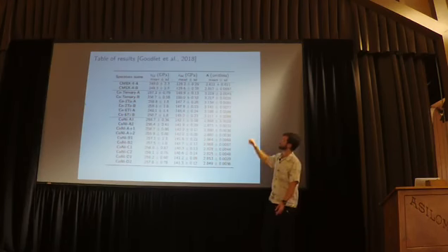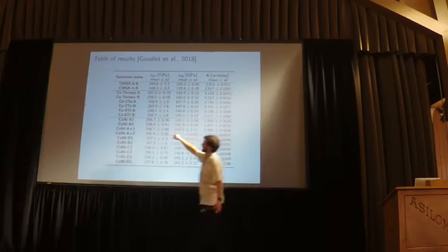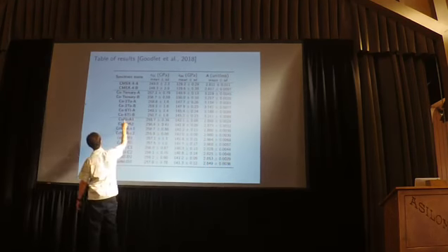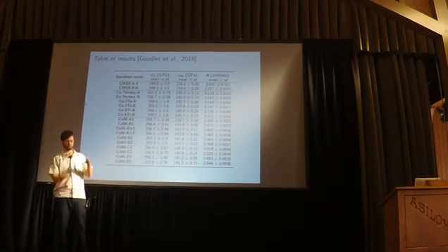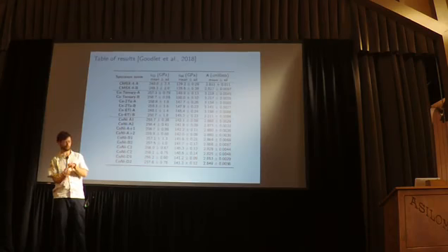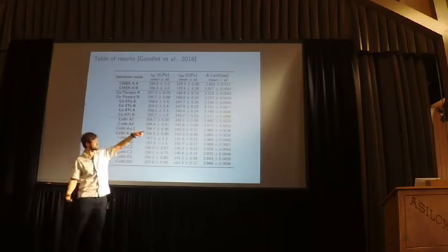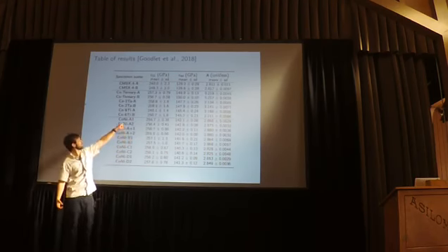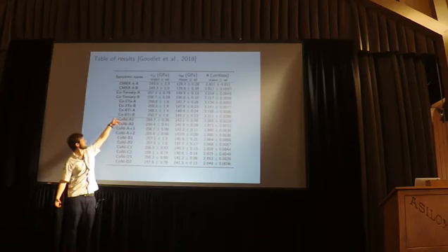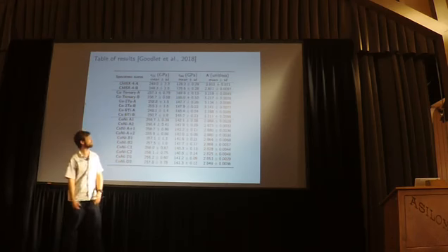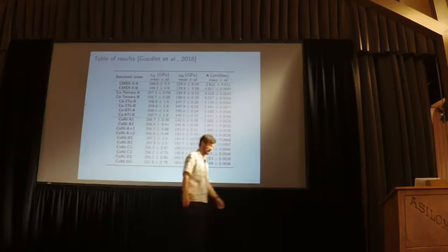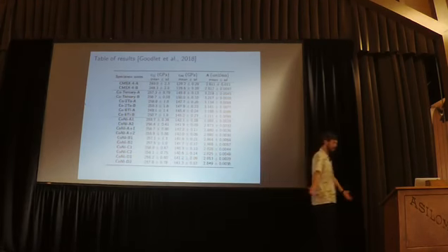In this case, we took a sample of some sort of cobalt nickel superalloy, put it in the little test rig, measured its resonance modes, and then ran a Stan calculation on it. In each case, we did a replication of the experiment. And so here you can see a bunch of mechanical constants and our uncertainties of them.